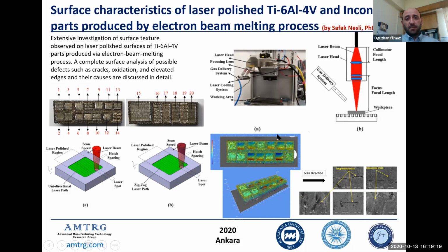We did many different experiments in order to find the optimum parameters for laser polishing of the surfaces, how we could improve the surface, and what the effects of the laser on the surface are, because we observed some cracks, oxidation, elevated edges, and so on. So we tried to improve the laser polishing process to make it applicable for improving the surfaces of additively manufactured parts, mainly the EBM parts.